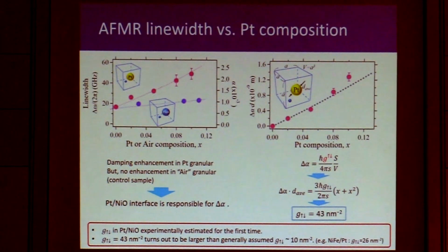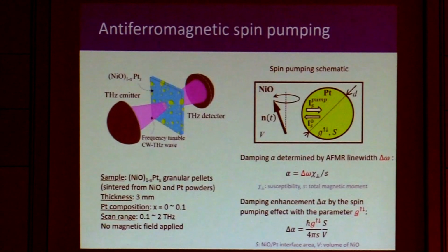So can you do the same experiment instead of mixing platinum with nickel oxide, just depositing platinum on the back, separated by a little bit of copper maybe, and then increasing the distance? That's the other way of doing it, with the single frequency. Yes, but for this technique, we need a volume. The thin film doesn't work here. So again, this is the best we can do. And right now, we are also replacing this platinum with something else that is considered to have less proximity effect. So from that difference in the result, we might be able to claim something more.